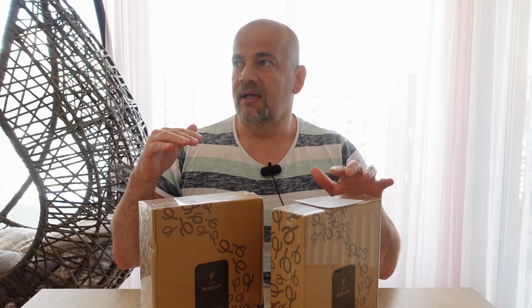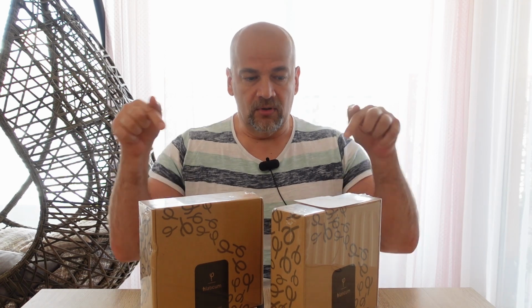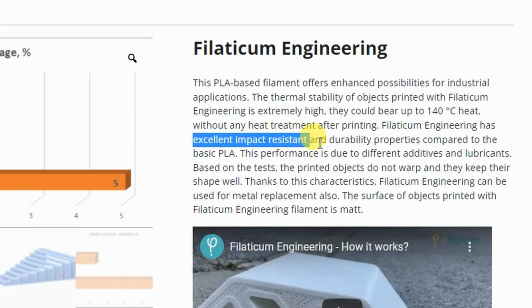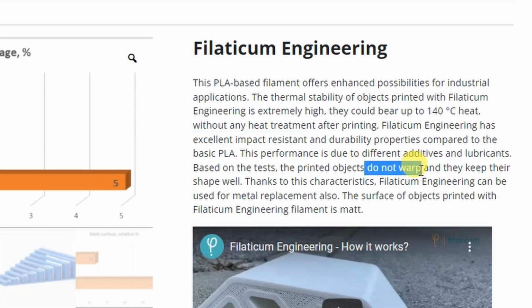I will do the regular mechanical testing with these filaments, so the results will be comparable not only between these two materials, but also with those which I did in earlier videos. They also claim that it has excellent impact resistance. It doesn't warp, which is again a big advantage compared to ABS. It has a matte finish, and they also claim that it can replace metal, but I'm not sure about this. About the engineering PLA printability, theoretically it should be printable like any other regular PLA, except that it requires a bed temperature up to 100 degrees Celsius.